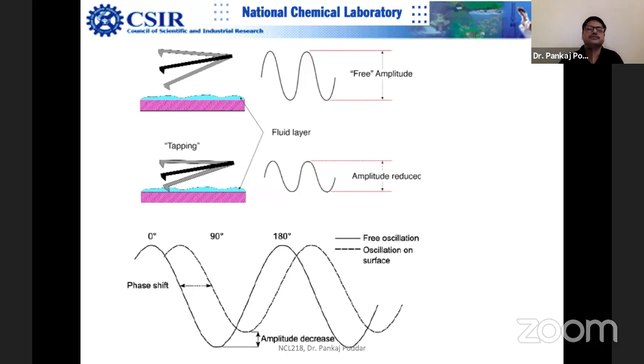So depending upon the force being larger or smaller, now as I mentioned, this tip is rapidly going in and out of this force range. So this is not a static force, it's a dynamic force. It's moving up and down, so the force is almost all the time changing. If the force is changing, then k is changing, and the frequency is changing all the time. A phase shift is also there. You can see that this is called phase shift, okay? And this is amplitude change. And the frequency change, you already know.